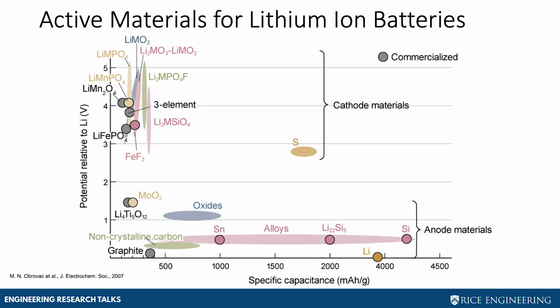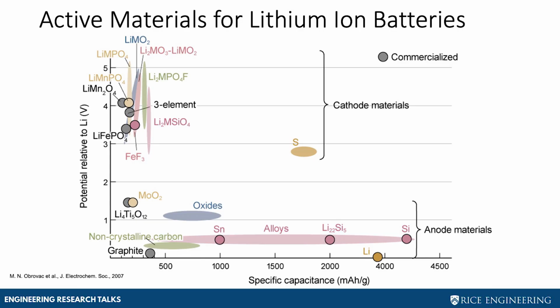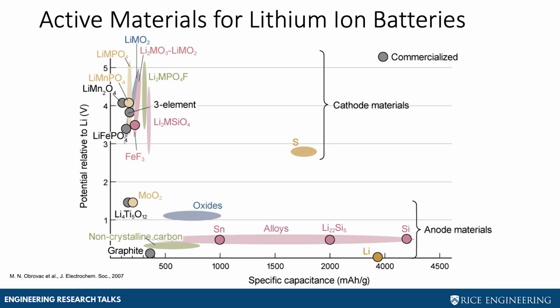So let's take a look now at what type of active materials we can use for lithium-ion batteries. So here I'm showing you a capacity plot as a function of potential relative to lithium. The lower potential values correspond to anode materials. The higher potential values correspond to cathode materials. In gray, I mentioned graphite. This is the most commercialized anode material for lithium-ion batteries. In the cathodes, we usually have some type of metal oxides. Lithium cobalt oxide is one of the most popular ones there. So as we're trying to push towards higher capacity, higher power lithium-ion batteries, we need to move up this capacity curve. And if you look here in the anodes, silicon is actually one of the top performers in terms of capacity for lithium. So why hasn't silicon been used?